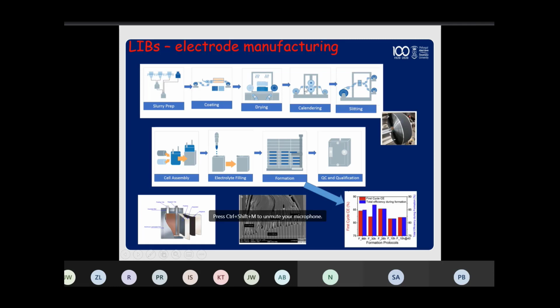Calendaring, again, this is applying a pressure to make it more compact. Again, it has to be optimized for porosity. So again, this influences how much lithium can go in and out. And then, of course, we have the slitting, and you end up with nicely coated, in this case, if it's a cathode, aluminum foil with your electrode. Now, imagine that all these parameters, all these various steps need to be optimized for a particular chemistry, for the particular slurry, for the particular solvents, and so on and so forth.